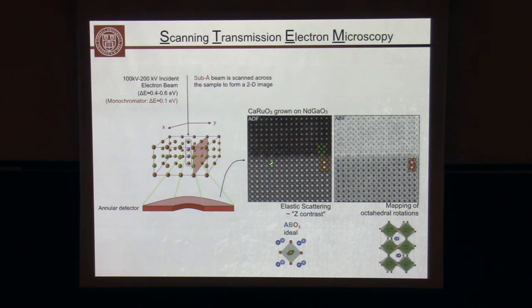If you notice that in this particular case, this annular detector collects a certain angular range of electrons. And if you go to very high angles, you're very sensitive to atomic numbers. That's why you see this bright dark contrast from the top to the bottom. Now imagine that we change the detector angle to go to much smaller detector angle. So we either make the detector smaller or we place it further away